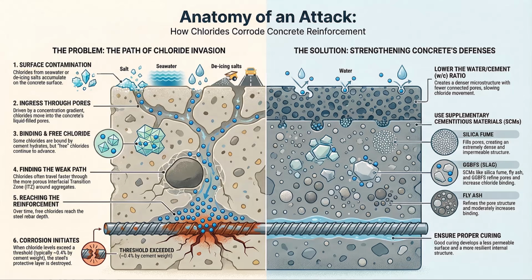It's a game changer. Typical effective diffusion coefficients for these high-volume GGBFS mixes drop dramatically, down to values between 0.3 and 2.0 times 10 to the minus 12. Which is a huge improvement over the OPC failure range. Massive. The second major player is silica fume, or SF, and that's more of a physical defense, right? It's all about density. Absolutely. Silica fume is an extremely fine material, and it's typically used in smaller dosages, usually 5 to 10%. Its strength lies in extreme pore refinement.